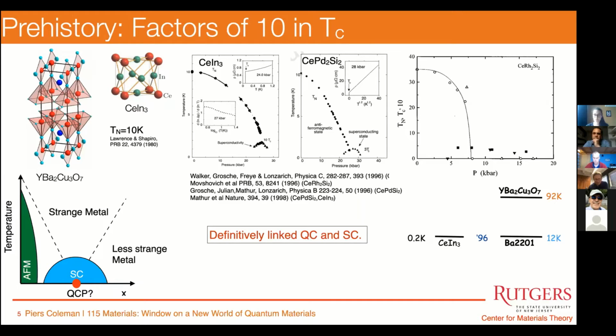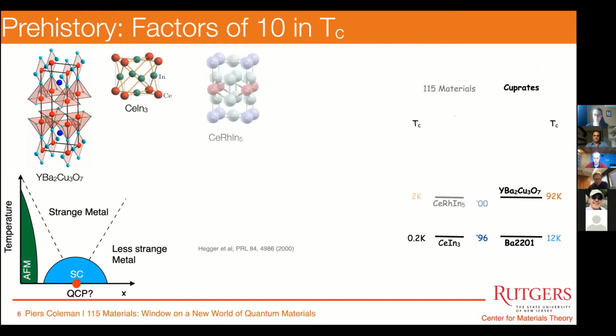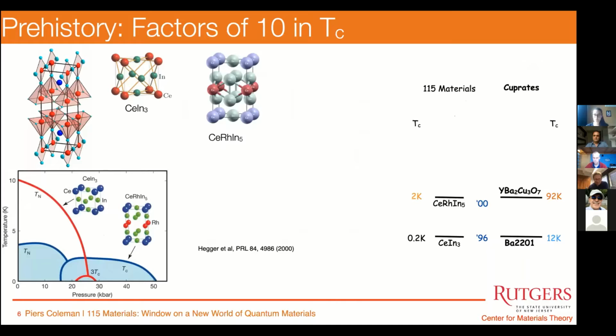And so enter the first member of the 115 family, cerium-indium-3, with this pathetically low superconducting transition temperature of 0.2 Kelvin. Now, just because a TC is low doesn't mean it's not interesting. And this led to lots of speculations. Well, what could we do to raise the temperature? And quantum chemists and materials designers of their era, working really as cowboys by the seat of their pants, such as Zach Fisk and also Gil Lonzarich and others, wondered whether cerium-indium-3 might be a starting point for new kinds of materials. And of course, what then happened was the discovery of cerium-rhodium-indium-5, which is literally cerium-indium-3 with another layer of rhodium-indium-2 spacing the layers. And of course, this system has a lower TC, T-Néel, but a much more substantial superconducting dome that forms beneath the quantum critical point. And this has become a poster child for our field.